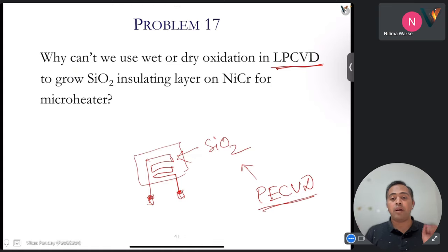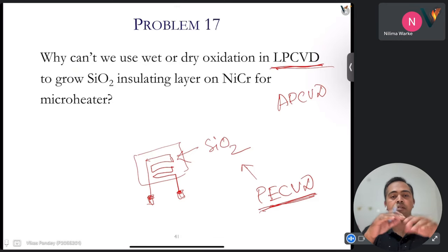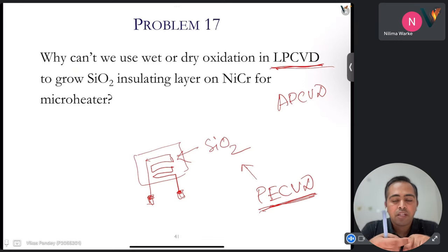So to avoid the heat: in the case of LPCVD and APCVD, heat is there, but in the case of PECVD, to achieve the activation energy for the chemical reaction at a lower temperature, not exactly room temperature but somewhat like 50, 100, we use plasma along with this heat. The plasma gives the activation energy and plasma is cold, and that is why we can go for this process in which our earlier structure, the microheater, will not get destroyed, as well as we will be